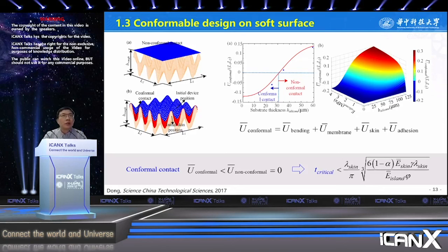The middle figure gives the effect of the thickness of the device. One can get the conformal condition. Certainly, the total energy is related to both the thickness and the elastic modulus of the device. The results are plotted in the right figure. One can conclude that epidermal electronics with low bending stiffness, smooth and soft skin, and strong adhesion promote the conformability.